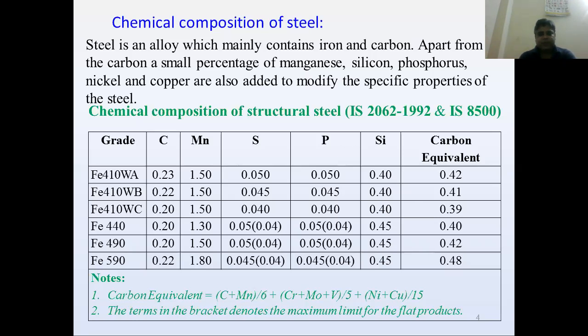Now Fe 440: carbon content 0.20, manganese 1.30, sulfur 0.05, phosphorus 0.05, silicon 0.45, carbon equivalent 0.40.